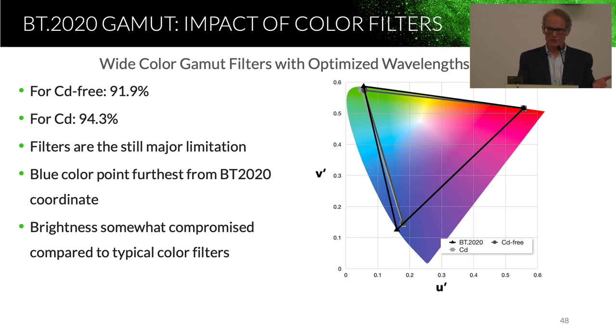But by doing that, of course, we've decreased the blue emission as well, and we've decreased the brightness of the entire display. So this isn't a fabulous solution, but it does improve the color gamut. When you do that, you get to 94% color gamut coverage for cadmium and 92% for cad-free. Now, there's a caveat here. Because of the broader emission from the indium phosphide, we had to move it further out to prevent it from contaminating the green quantum dot. And to do that, we took a big hit in brightness. So the cadmium-free one, that's almost 92% gamut coverage, also has 25% less brightness. So we paid a big price for getting that gamut.